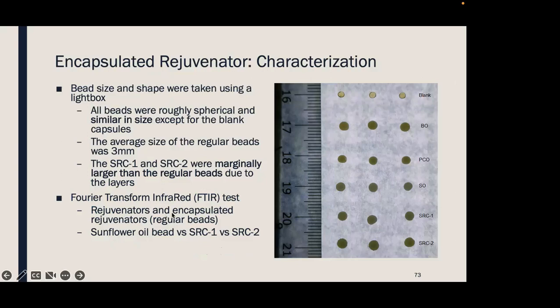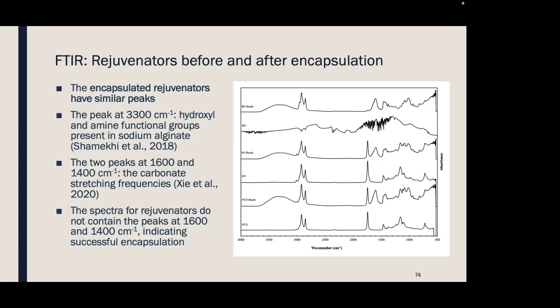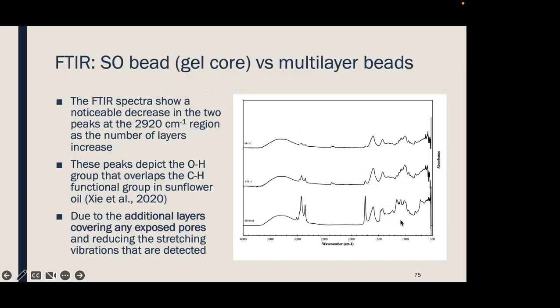And here you can see we've also done Fourier transform infrared tests, whether or not the material is actually encapsulated well. And you can see before and after encapsulation, the peaks actually match over here. So some of the rejuvenators do not contain the peaks between these spectra, indicating that it's actually successful in terms of the encapsulation stages. Okay, I meant to click on this so you can see this particular thing here. Okay, so that's good. What else do we have here?